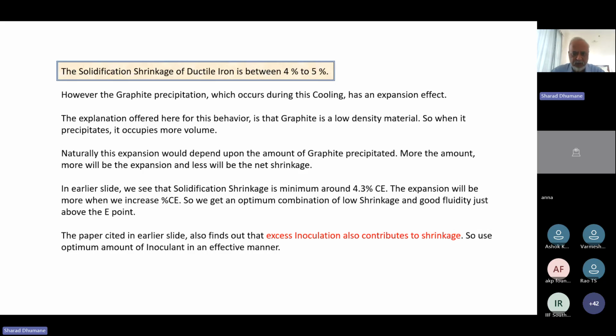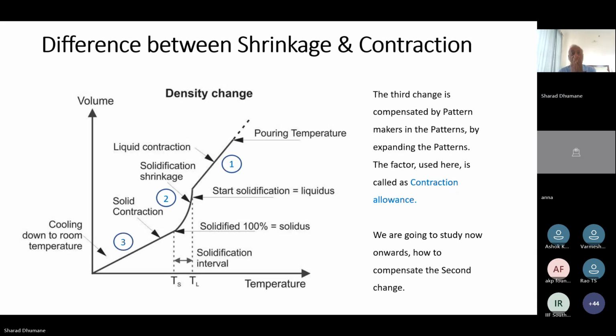So when you have seen a lot of microstructures and correlated them with the amount of inoculation, you will come to know yourself, in your conditions, with your materials, in your furnace, at your pouring or melting temperatures, what is the optimum amount of inoculation. I think this is very important, and everybody should understand what is the optimum amount of inoculation in their foundry, because it changes from foundry to foundry. So you find out what is the optimum amount in your foundry. Okay.